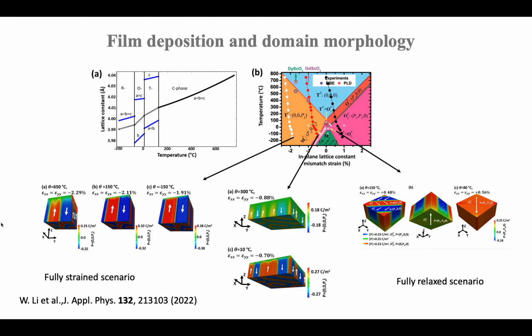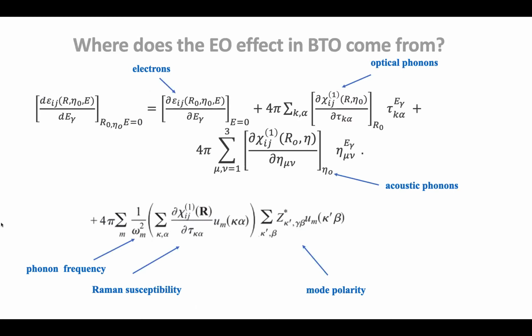Right? And so I think different people cool at different speeds. It depends. If we have very thick things, we have to cool slowly, otherwise they crack. But if you have a very thin film, you can cool really fast, like 30 degrees per minute. And the microstructure will be different, and then it will give you a different electro-optical response. All right. So now we're going back to saying what actually is this electro-optical response.